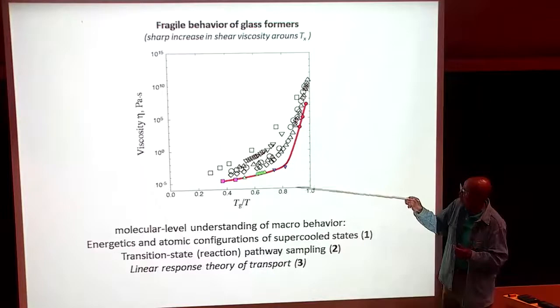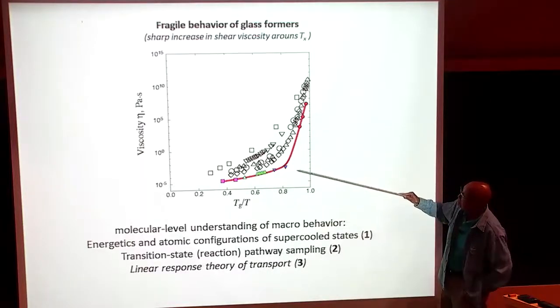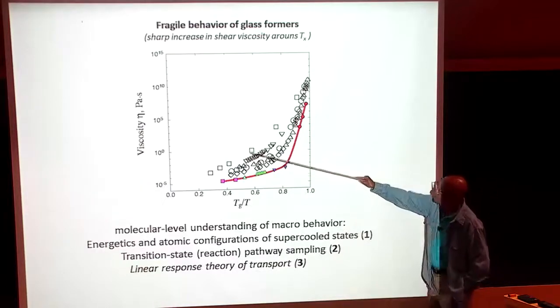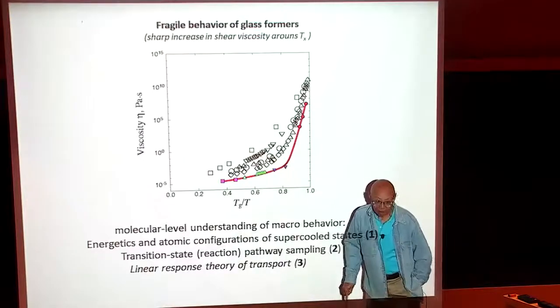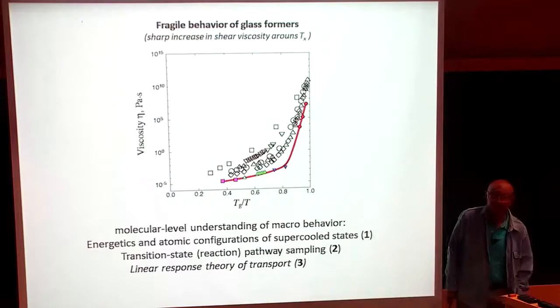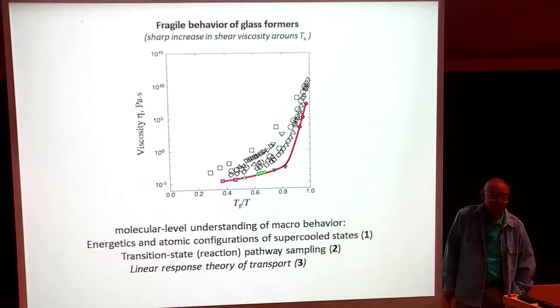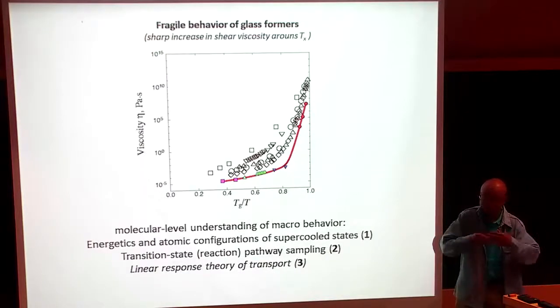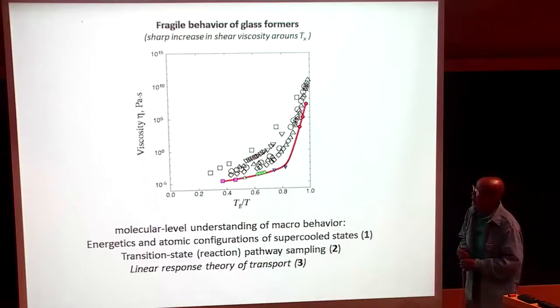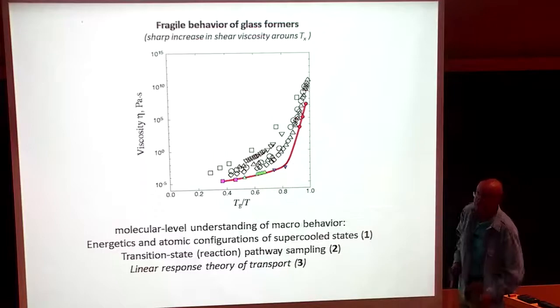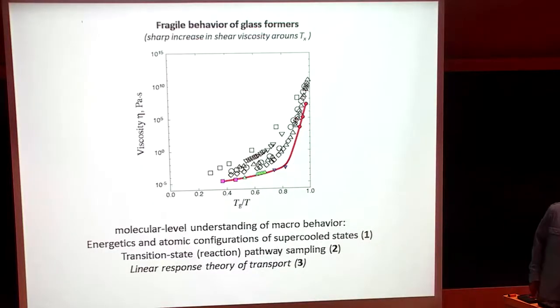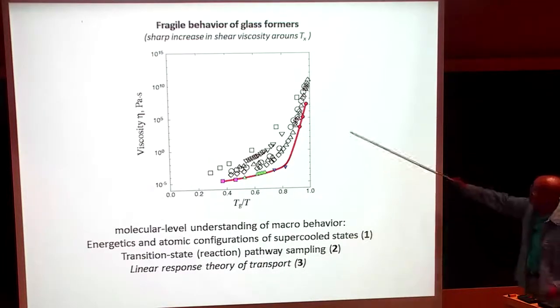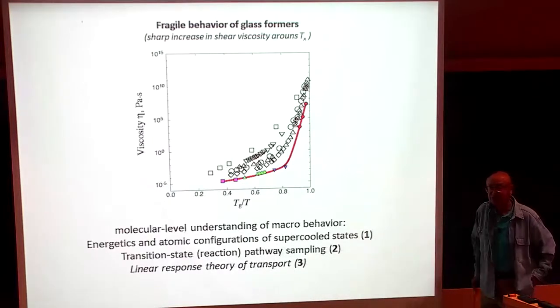And that's reflected in this as well, because you might say, well, not that many people care about viscosity, although I would argue otherwise. But just remember that the viscosity can be expressed as the product of a shear stress and a relaxation time. Okay, that's dimensionally right. It makes sense physically because viscosity is transfer of momentum, shear stress. When this thing goes through 10 orders of magnitude, the shear stress doesn't change that much. A liquid has high frequency shear, not zero frequency shear stress. Going to a glass, the shear stress may change by 2 orders of magnitude. And if you have 10 or 12 orders of magnitude change here, you have 9 orders of magnitude change in the relaxation time.